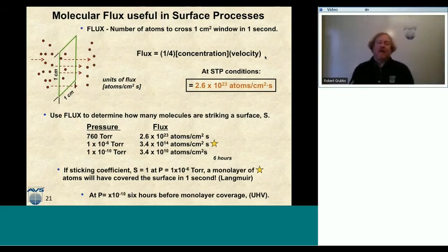Now, another concept that I want to run past you, which is actually very important, is molecular flux. And I'm sure in your physics classes you've talked about flux or magnetic field flux. Well, this is a similar concept. Flux is just the number of atoms that cross a centimeter squared window in 1 second. So I hope that you're seeing a general theme here, that we're boiling things down to centimeters squared. So we know that we have 10 to the 15 sites per centimeter squared. We know that we have 10 to the 22nd water molecules per centimeter cubed. But now I want to talk about a dynamic process of how many molecules are actually flowing through a 1 centimeter squared area at a given pressure.